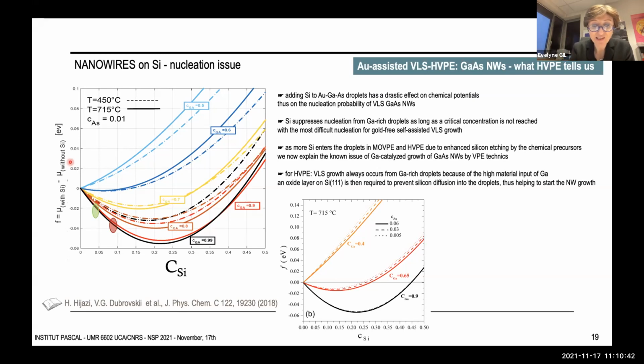And of course, pure gallium-assisted growth, when the concentration is close to 1, is the most sensitive to the presence of silicon. So we can see here that silicon suppresses nucleation as long as the droplets are gallium rich and as long as a critical concentration is not reached. So as more silicon atoms enter the droplets in MOVPE and HVPE because of the enhanced silicon etching by the chemical precursors, we can now explain the known issue of gallium-catalyzed growth of gallium arsenide nanowires by the VPE techniques. And for HVPE, VLS growth always occurs from gallium-rich droplets because of the high material input of gallium. So it means that we need an oxide layer to prevent the silicon diffusion into the droplets, then helping to start the nanowire growth.